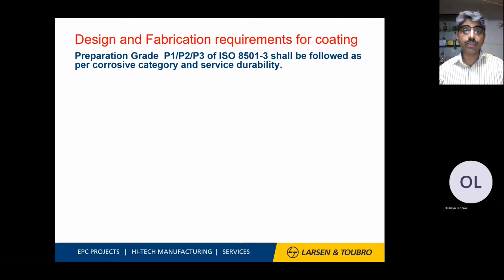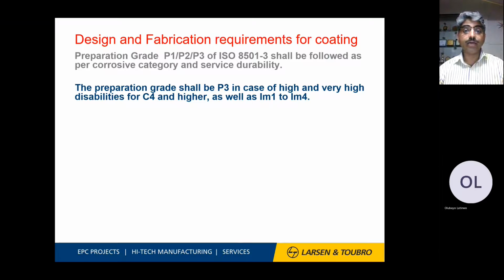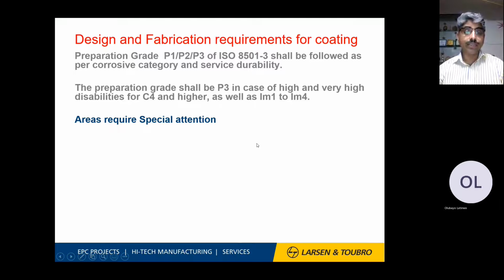Here, the category is given based on the service durability, and that gives good value for the coating which we select. The better the surface preparation, the better the quality and life of the coating. If the preparation grade is P3, that is very high, for a very highly stressed case. C4 is the corrosive environment, so C4 and higher gives a good surface finish. Even the immersion categories, IM1 to IM4, give you a good understanding about the design of any particular coating in the corrosive area.